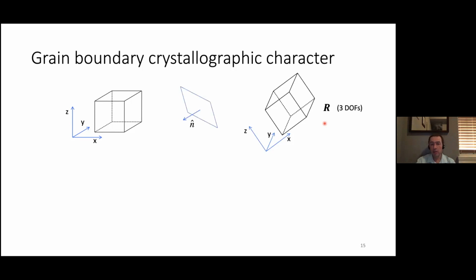The other thing that you need is the orientation of the grain boundary plane. Okay, so basically the plane in space, the orientation of the plane along which the two boundaries are going to be joined. Mathematically, whenever we describe plane orientations, we do that using a unit normal vector. And of course, in 3D, the number of independent parameters that are needed to specify a unit normal vector are 2. So there are 2 degrees of freedom associated with the grain boundary plane orientation. Altogether, we have 5 crystallographic degrees of freedom for a grain boundary. So the crystallography of a boundary forms a 5-dimensional space.